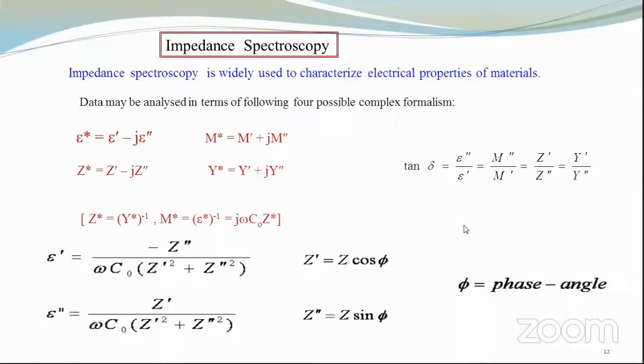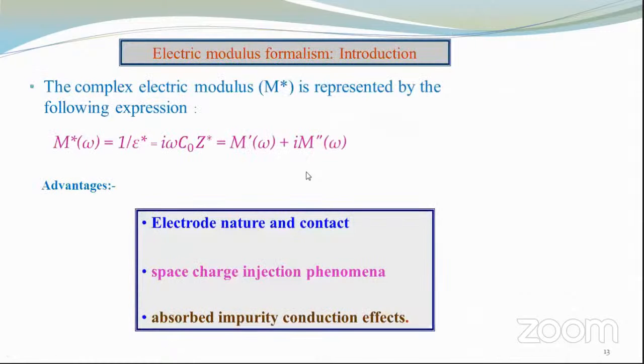So we have adopted a way to characterize the electrical property. We have adopted impedance spectroscopy, using these various formulas, for various electrical parameters like complex permittivity, complex electric modulus, complex impedance, and complex admittance. And these are correlated with these formulas. Using these formulas, we have characterized the material. And we have adopted the electric modulus formula in this case, because it is just the inverse of the complex permittivity, which gives the complex electric modulus.